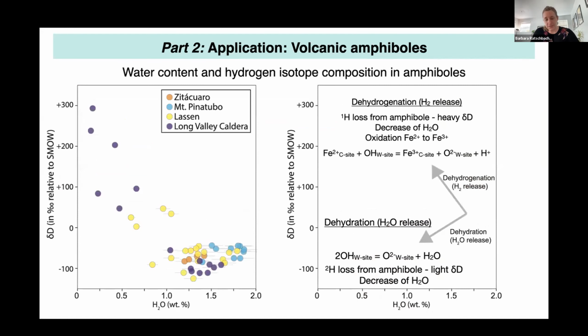So now the important part really is to figure out whether the ferric over total iron ratios we can analyze represent magmatic conditions or if they have been modified after crystallization. And in order to do that, we can look at the water content and the hydrogen isotope composition of the amphiboles. The reason why those two parameters are helpful in answering this question is because there are two processes which are capable of modifying amphibole chemistry after crystallization. And these are dehydrogenation and dehydration. So on the right side here, you can see that the process of dehydrogenation, which is basically the release of hydrogen from the amphibole structure, causes a decrease of the water content in amphibole, but at the same time also a trend towards heavier, higher hydrogen isotope composition.